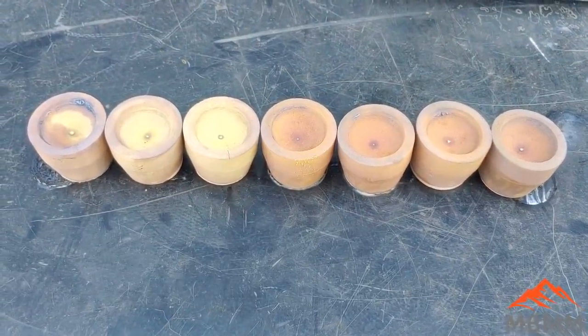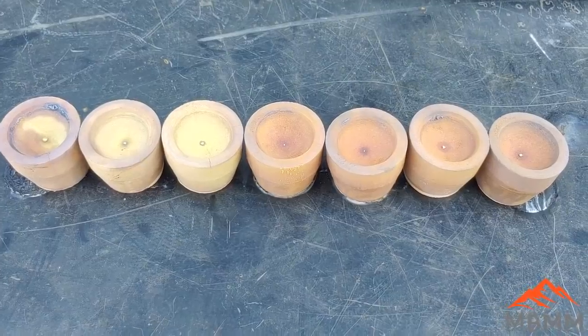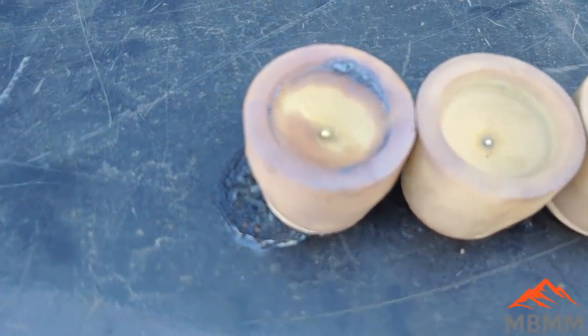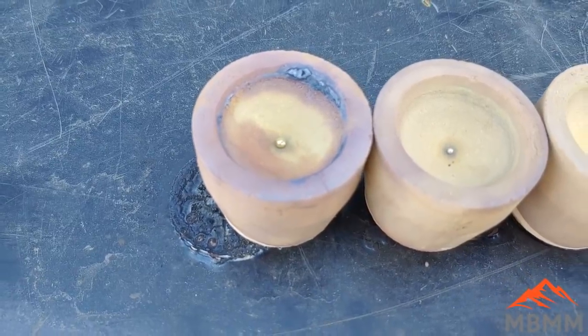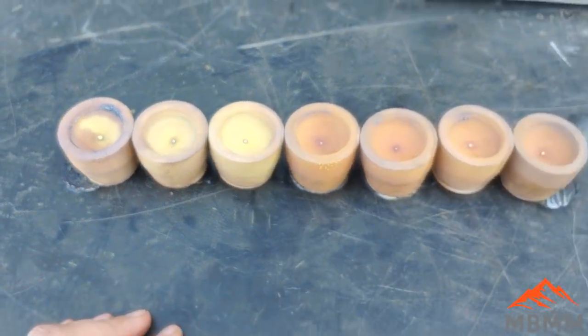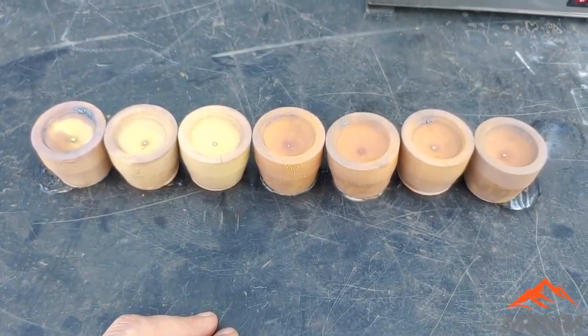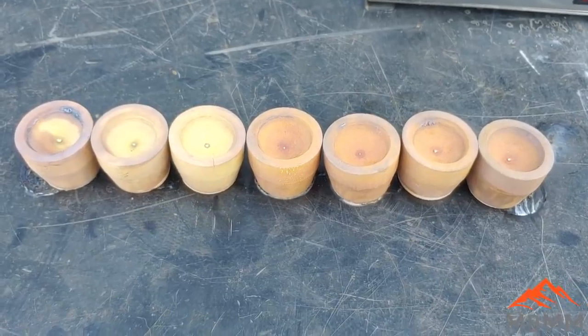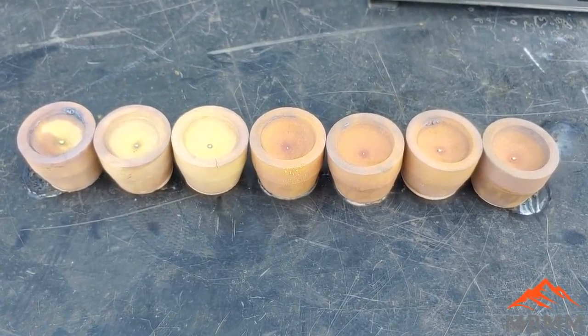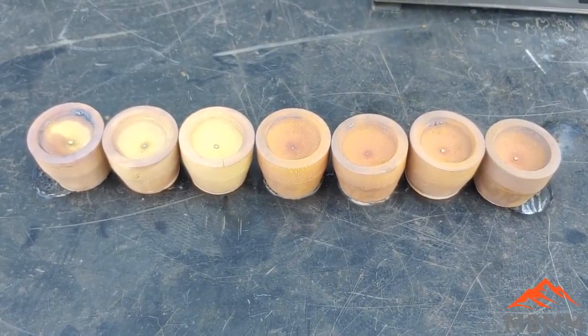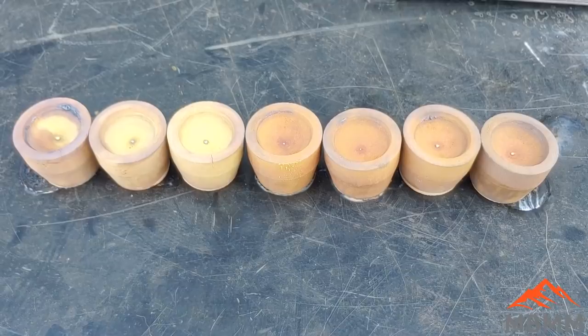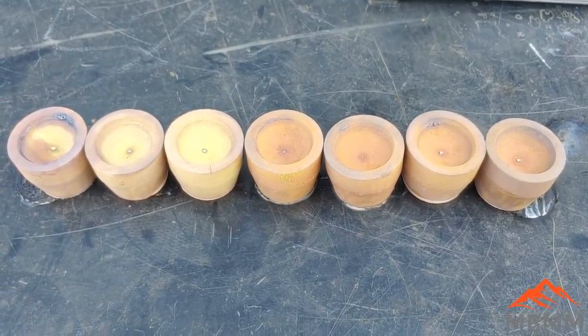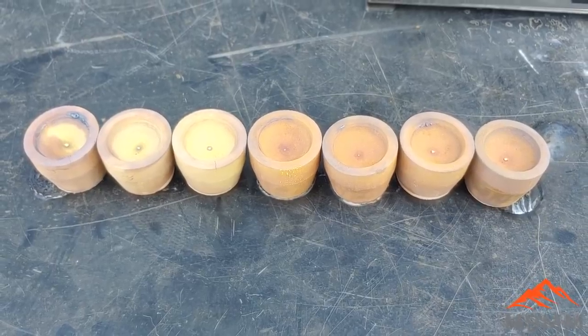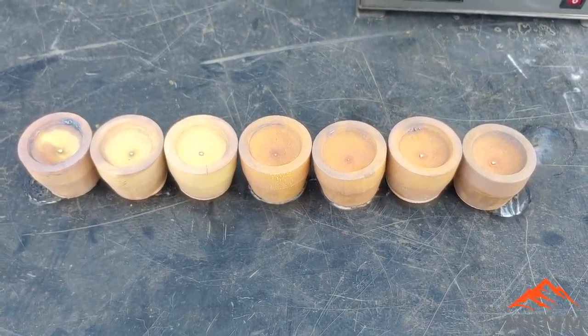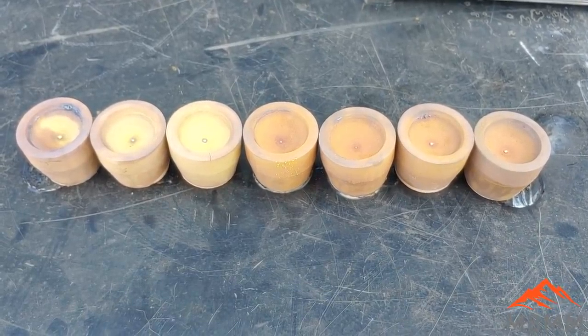You can see that all the beads are different sizes, which is to be expected because they're not all the same grade. And this one is clearly the best. That's actually a pretty good sized bead from 120 grams of material. But you can see the cupelling process here. What it does for you is that all the base metal oxides are absorbed into the cupel, and you're left with only the precious metals. So you have gold, silver, and any PGMs, platinum group metals, left in your bead, because all the other metals, the base metals, copper, lead, zinc, iron, all oxidize in the furnace and get absorbed into our cupels. So I hope you guys enjoyed the video today.